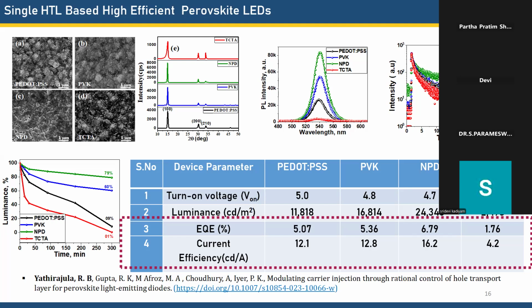In the left bottom, the luminescence in percentage versus time, we studied up to 300 minutes. Here you get the maximum for the green color one, which is the NPD based device. In the perovskite devices, the remaining ones are not retaining, but our NPD based device retained up to 79%. Degradation is happening. Most probably the cause is ion migration happening inside the device and the thin film. That might be the possible reason it is not retaining the light.